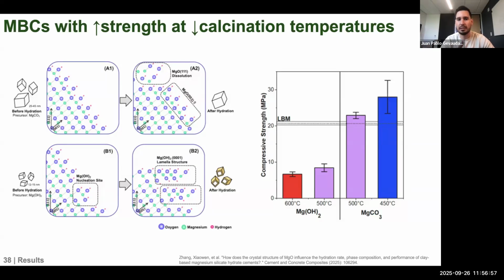And again, it's all because the hydration, the phase assemblage, and the performance, in this case mechanical, are really interlinked together. And something that is really cool that we show here is that less is more. Less magnesia can actually lead us to higher compressive strength and also lower calcination temperatures, which means that we emit less CO2 in the production of this magnesia for magnesia-based cements. So this is a really interesting and fascinating opportunity here. And again, if you want to learn more, please check out our paper, which I have linked here at the bottom.